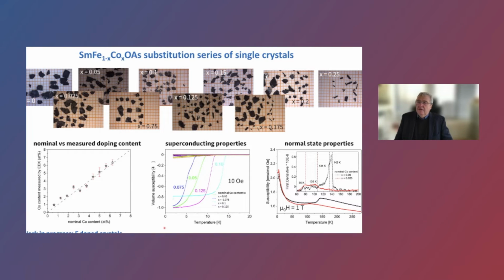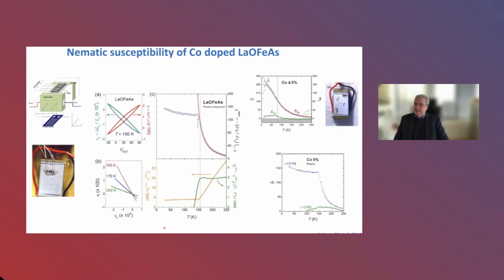Now let's have a look at this aspect which I would like to emphasize today, and that's this nematic susceptibility. So having these single crystals now, we can follow this approach, which has been pioneered by Ian Fisher a decade ago on these 1-2 compounds, where he used piezo elements to apply a tiny strain to the sample and measure simultaneously the resistivity. And you can do that in different configurations as shown here. So you can probe different modes, and there you can really address in particular this nematic instability, or this nematic susceptibility as people call it. So if you then measure the resistivity as a function of these tiny strains, so look at the numbers, it's 10 to the minus 4 strain only, then you see the strong change of the resistivity as a function of this strain.